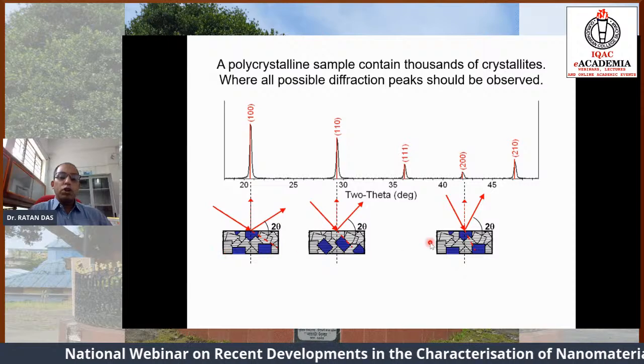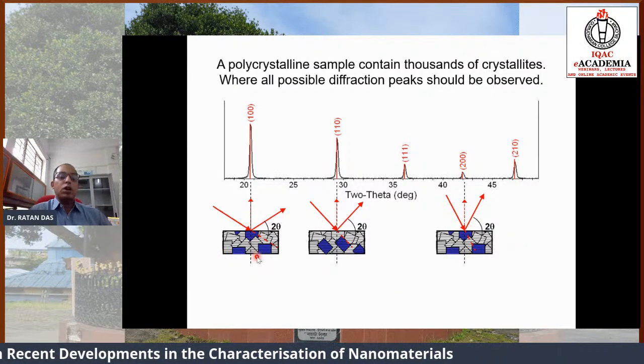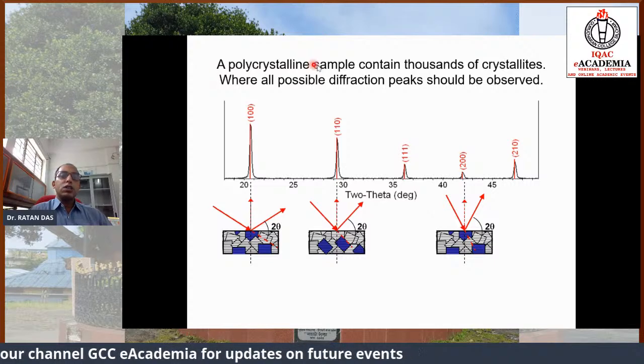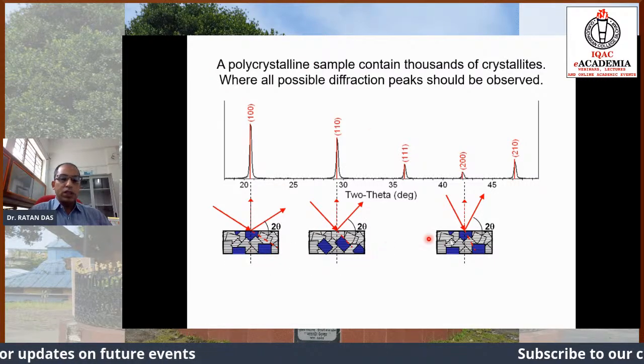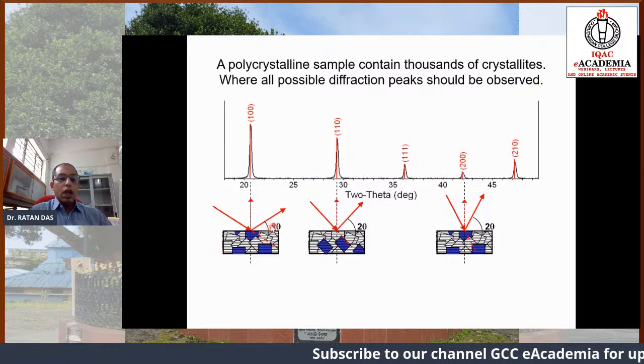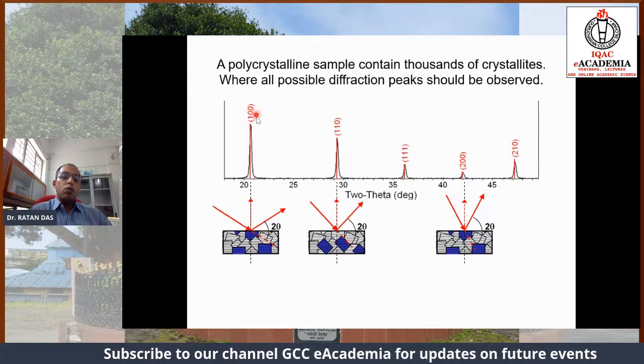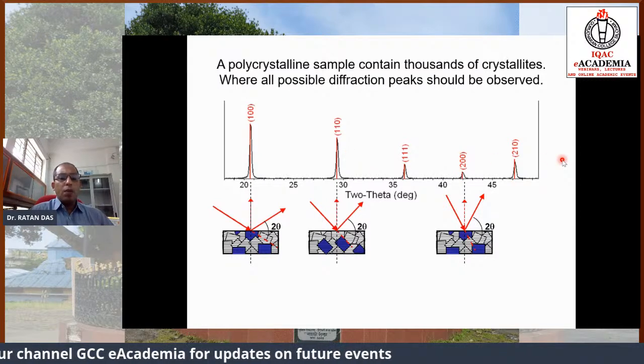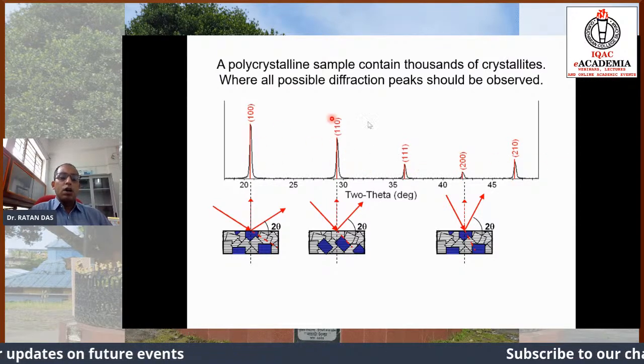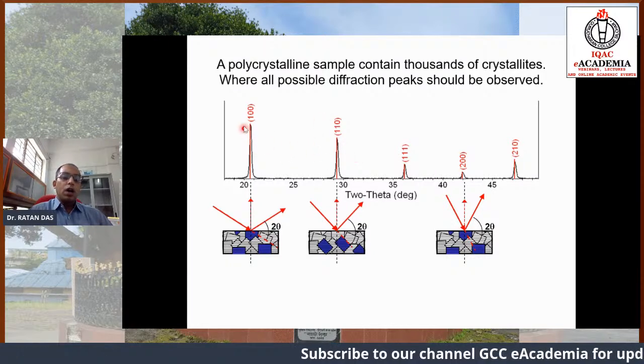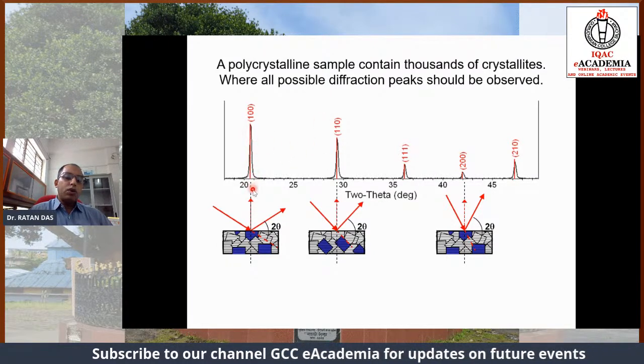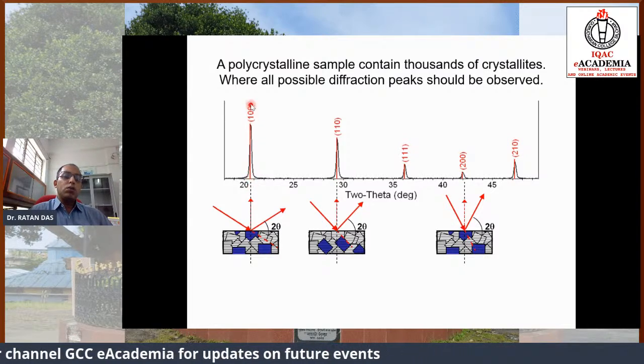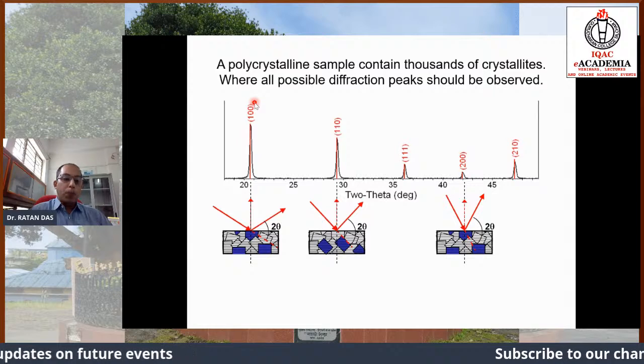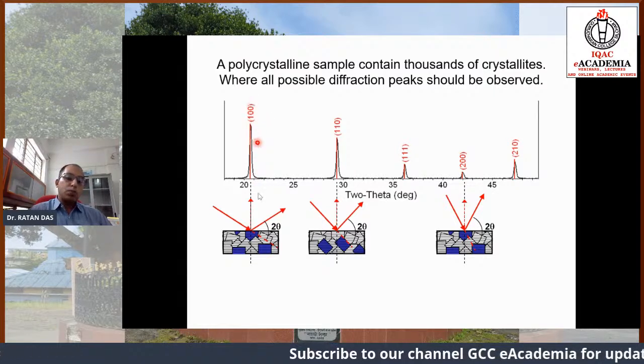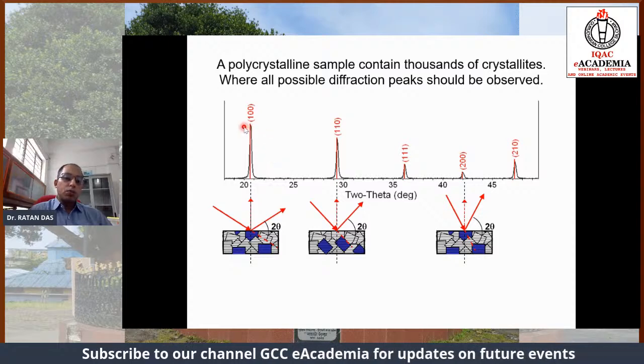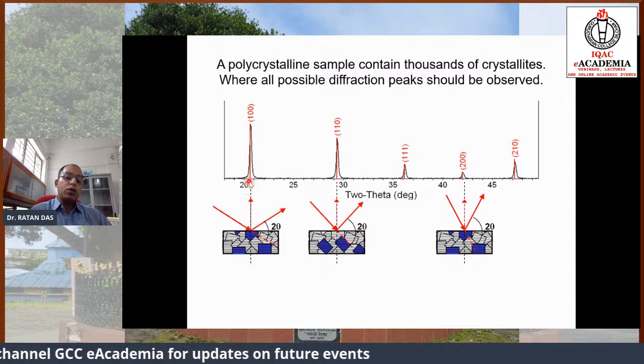But we are interested in polycrystalline nature because most of the nanoparticles are polycrystalline in nature. A polycrystalline sample has different crystallite sizes or different planes available in that particular structure, and we shall obtain different planes. You see, this is an arbitrary pattern that is given in the data. Here in the figure, at a particular angle of 21 degrees, we have obtained the 100 plane. Because of the presence of the 100 plane, the diffraction pattern with higher intensity is available at a particular angle.